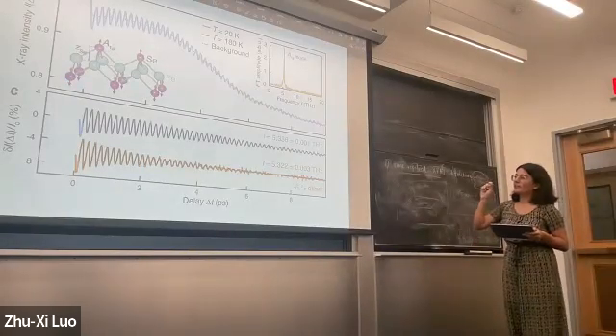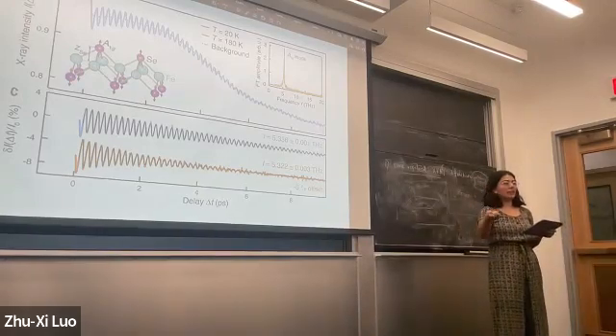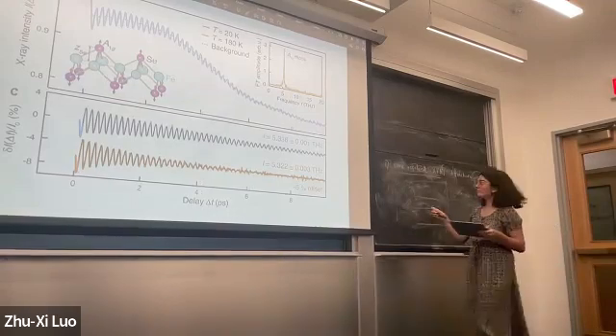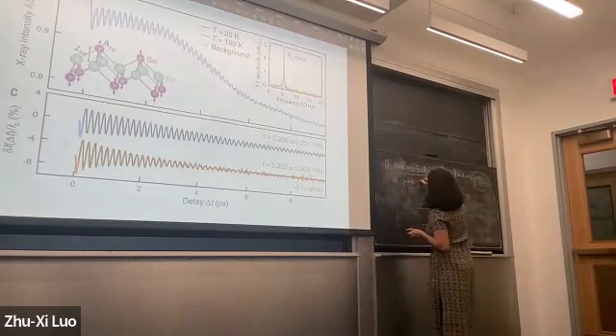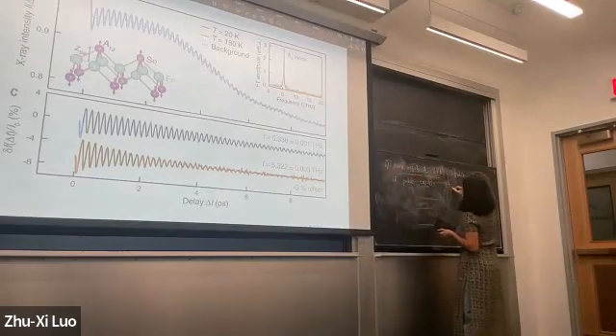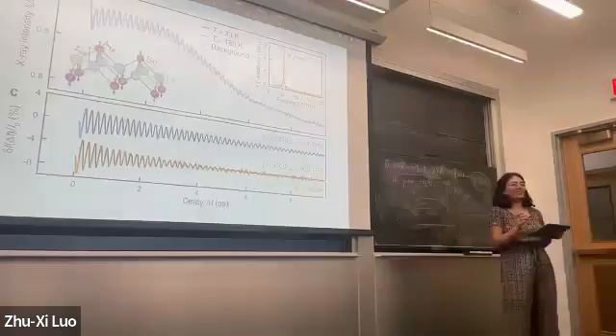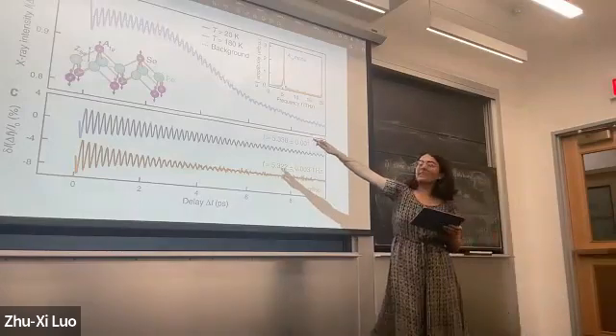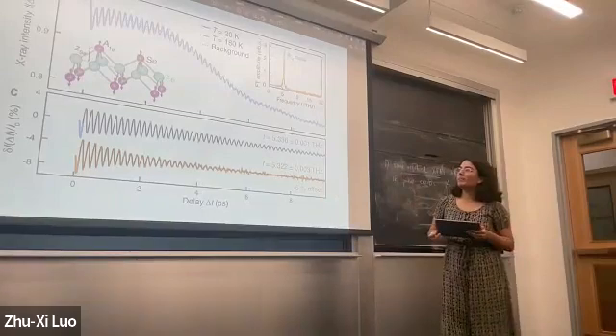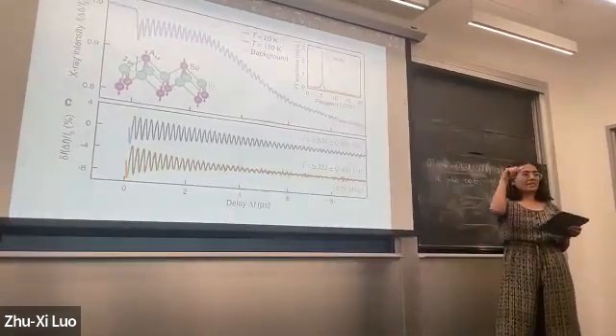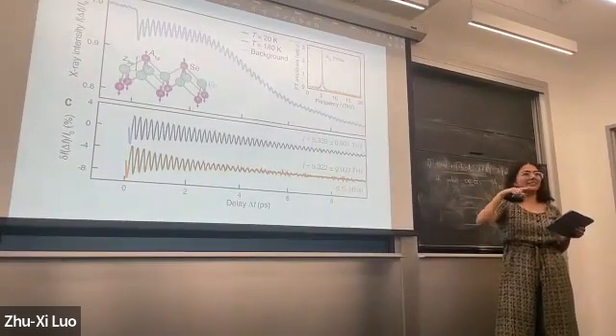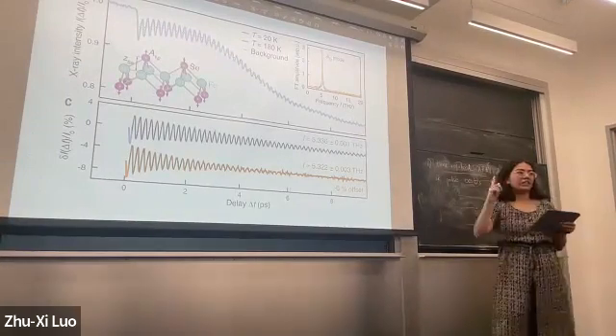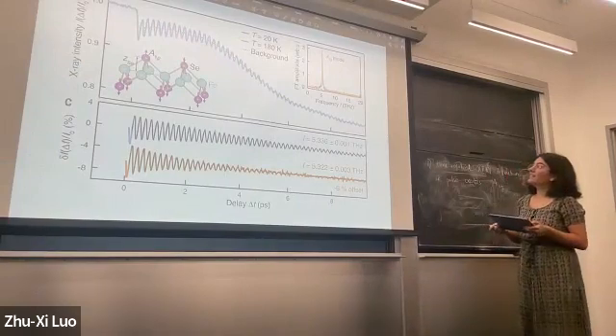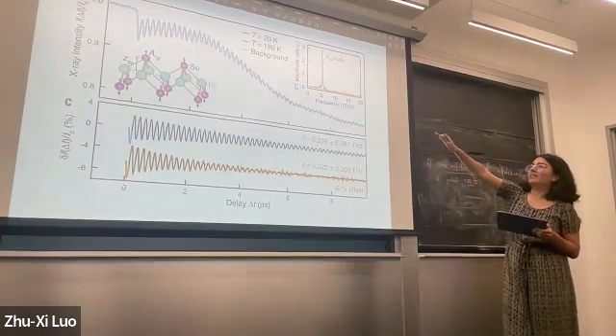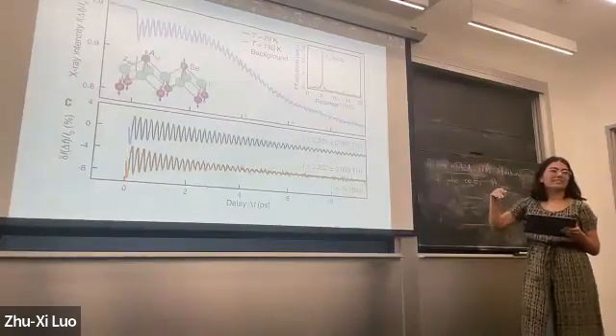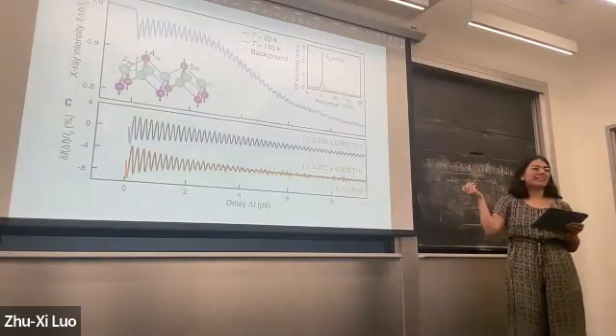And the claim is that this initial IR pulse coherently excited this particular phonon, the A1g phonon. You can see the crystal structure of this material up there, and the selenium atoms are purple, and this is the mode corresponding to them bouncing up and down, so the angle between the iron and the selenium changing. And they indeed see that their X-ray intensity signal shows this oscillation at the frequency expected for this mode.